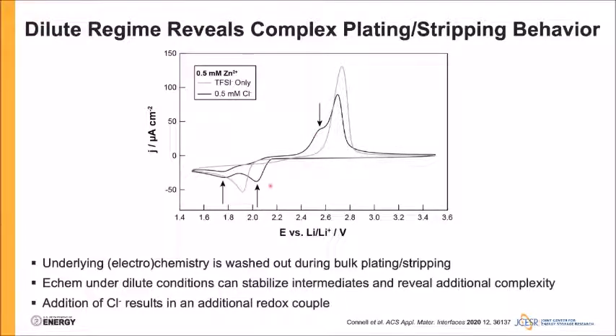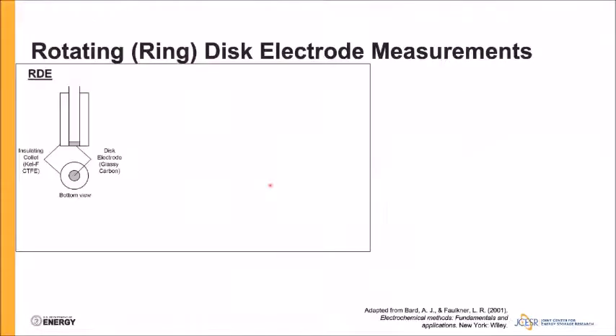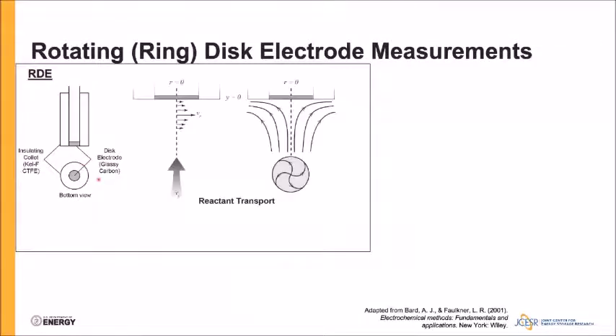And because we're working in dilute conditions, we can utilize rotating disc and rotating ring disc electrode techniques. Just as a brief refresher for those who may not be super familiar with these techniques, the idea of an RDE measurement is you have a cylindrical electrode that's embedded in an insulating collet. If you induce rotation of this electrode, you can force convection of your reactants to the surface of the electrode and set up a constant delivery of your active material to the electrode surface.